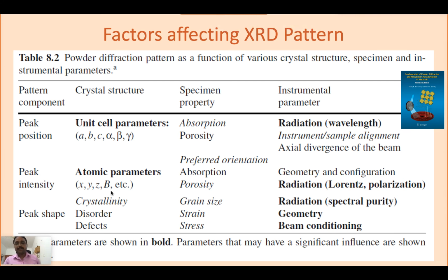Then what about peak shape? Here, all the nano people working, we should be very careful. Peak shape determines your grain size, strain and stress. Very, very important, because sometimes the broadening, that is the peak shape, takes the name peak broadening. Whenever people are getting a broadened peak, they will say my sample is nano. Please be careful, that can be due to the instrument also. That we are going to see in the next slide.